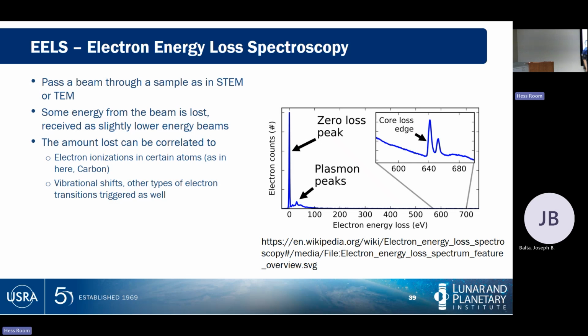So if I am the detector and there's an electron beam being shot through, this main peak right here is the beam that's going straight through. These other peaks just off to the side are electrons that have just lost a tiny bit of energy, but they've lost that tiny bit of energy by interacting with my sample. This is another thing I could technically measure. How much energy has been lost to the material?